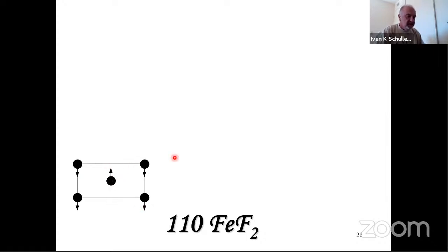Let's say we take the 110 FeF2. This is an antiferromagnetic compound. And we take that surface. So there it is, how the 110 FeF2 surface looks like. There are four spins pointing down in the corner and one spin pointing up in the middle. These are only the iron spins. The fluorine spins are somewhere in between there, and they are providing the glue to stick all this together. This is an antiferromagnet, because if you look at the spins here in the corner, there is a quarter of a spin pointing down, and four times a quarter is one pointing down, and there's one spin pointing up. So this is a totally compensated magnetic material, but it has some spins pointing down and some spins pointing up.